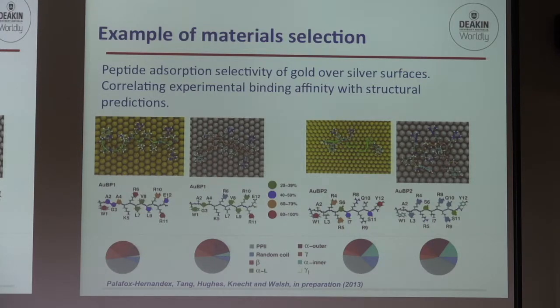They have a very similar lattice constant, which means the spacing between the atoms is very similar. So you can't just say, well, it's because of some kind of lattice matching argument. That doesn't really work. They have slightly different chemistries, and silver's more reactive. And what we're trying to do is predict the structures of these peptides on the surface, and then relate this to the binding affinities that are being measured in the lab.